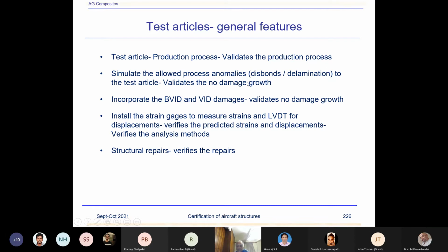Simulate the allowed process anomalies. Another thing is just to demonstrate that any undetectable damage or detectable damages do not propagate or create any detrimental effect on the structural integrity. So production anomalies like disbonds, delaminations were created at the time of manufacture, because that is a compliance requirement. We have to consider any damage which is undetectable that could occur during production, like delaminations or disbonds. And then incorporate the BVIDs and VIDs. BVID, barely visible impact damages, and then VIDs, visible impact damages, to validate no damage growth. That is a criteria of the structure.